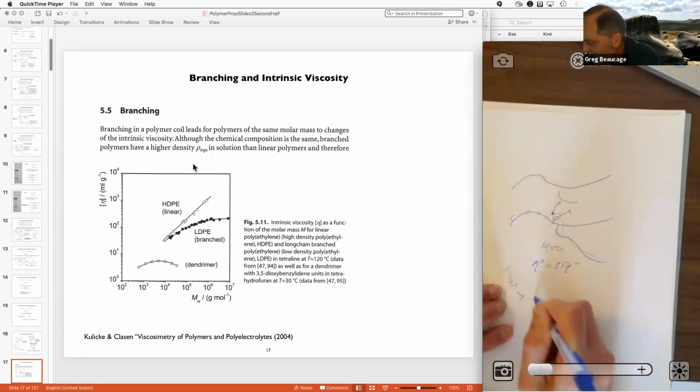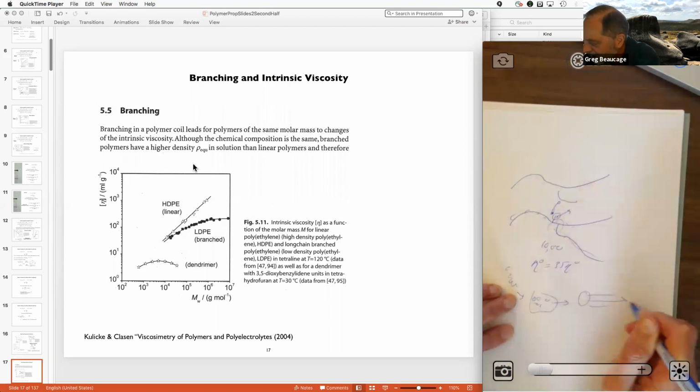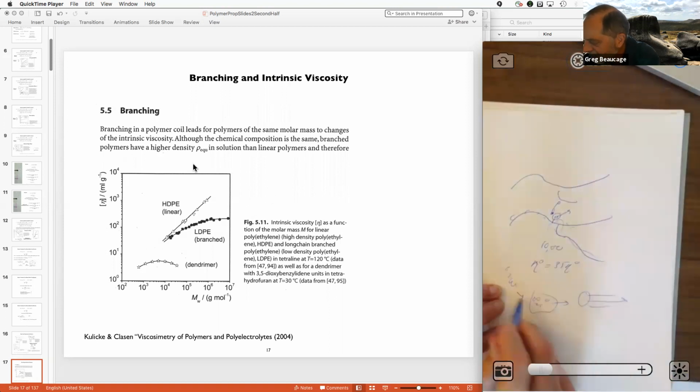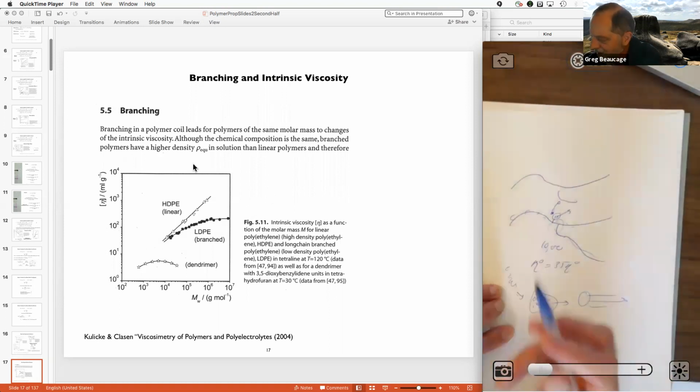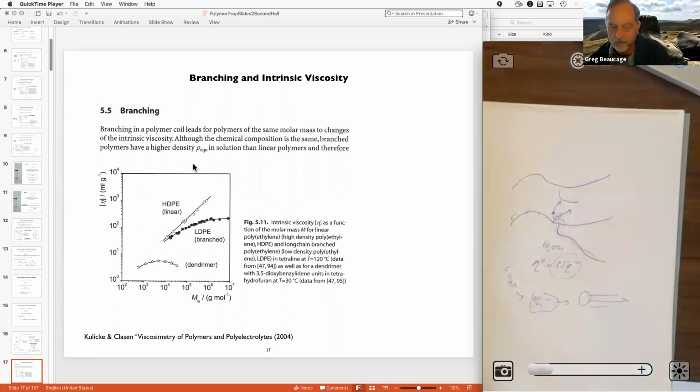So you make pellets that are going to be shipped by train to someplace. They're going to be put in another extruder. Then you make a part. So it's heated up two times, and both times you can introduce these long chain branches. The viscosity can go through the roof for that. So basically, people in the polyethylene industry want to know about this branching issue. So it's an important topic.